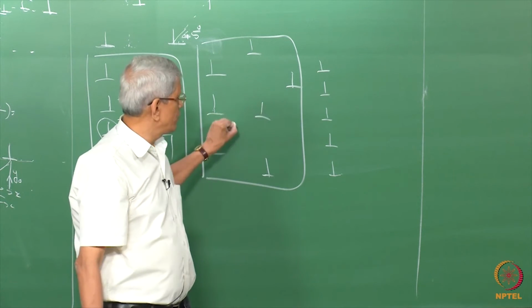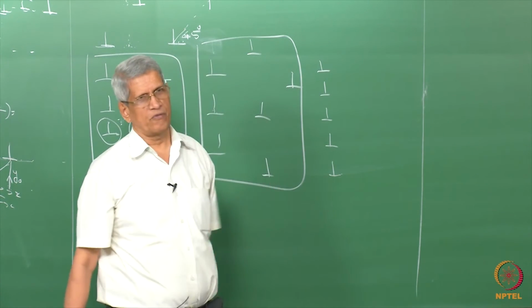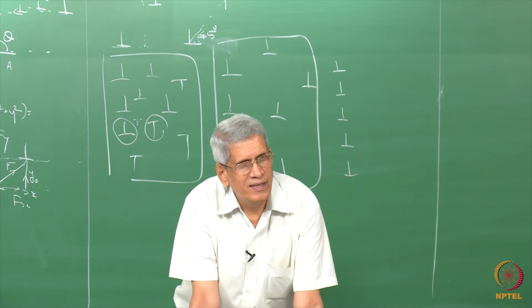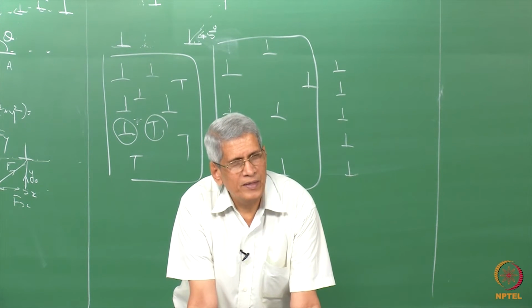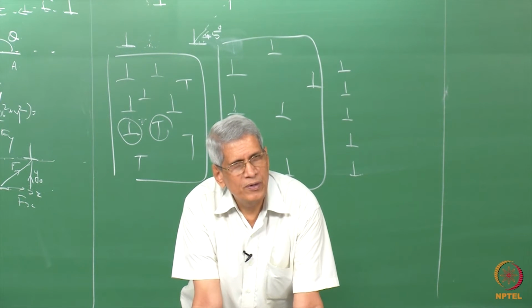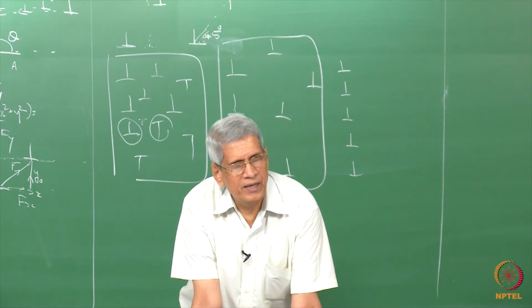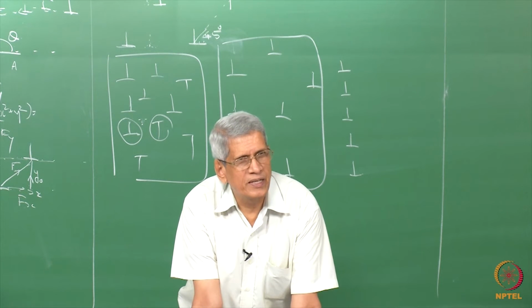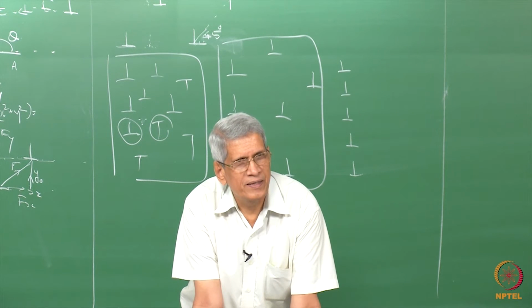If they arrange in this sort of configuration, the forces between the dislocations get reduced considerably. This is a more stable configuration. This is how, during the recovery process, a lot of small angle boundaries are generated in the material.